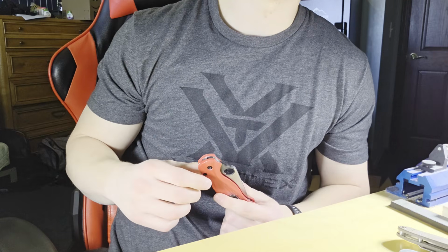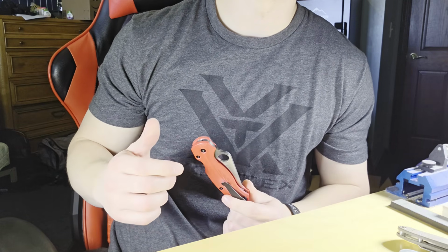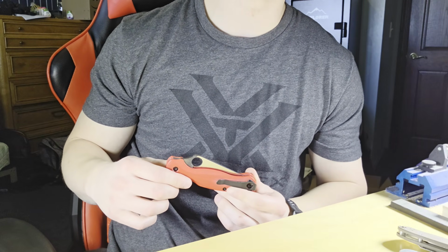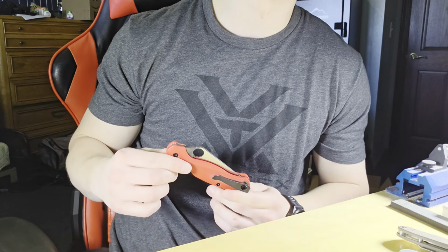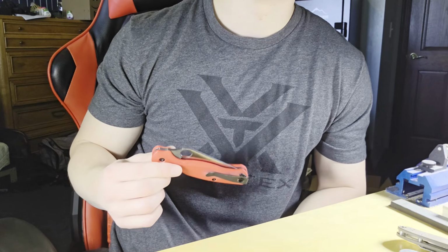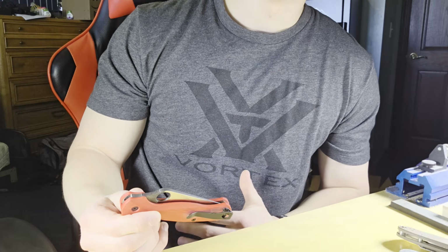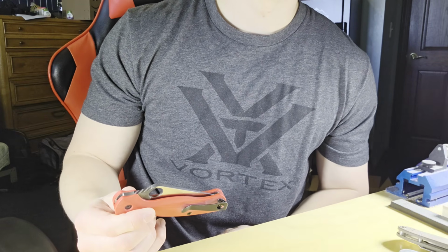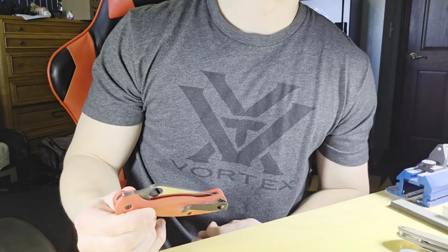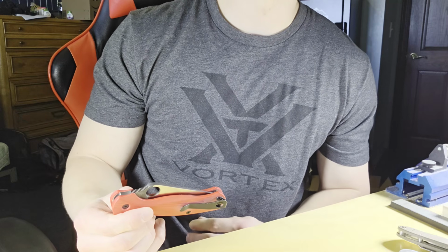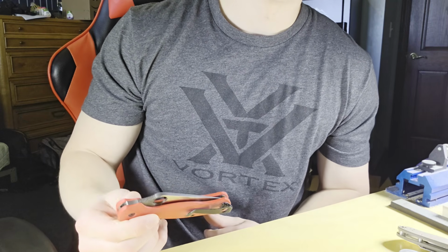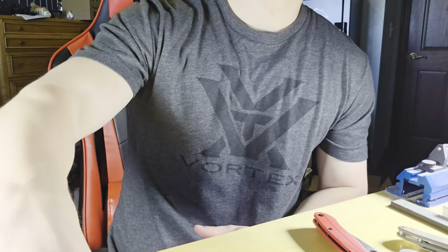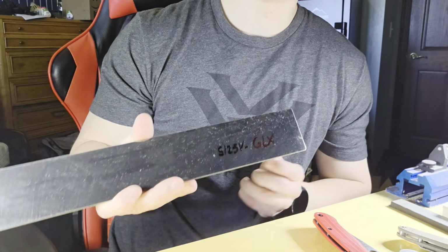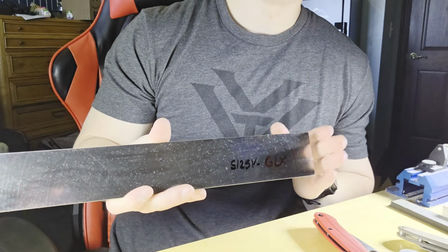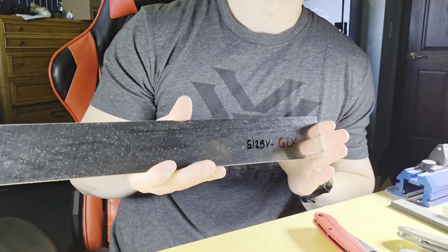The other sacrifice that isn't quite as obvious is the carbide volume. Higher hardnesses require higher austenitizing temperatures, which is the temperature the steel is soaked at during heat treat. And there's an inverse relationship with austenitizing temperatures and the amount of carbide in the steel. The higher the austenitizing temperature is, it leads to more carbide being dissolved into solution, which means there's less available to help in wear resistance. Steel actually has the most carbide volume in its annealed state, like this, just in a bar. This bar of S125V has the most carbide it's going to have right now in this state.